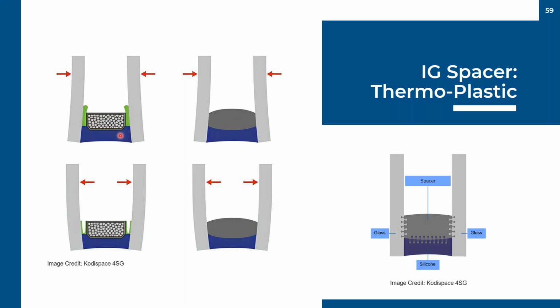Now, many times the problem with windows that we see all over the place, insulated glass windows, is they fog up, and that's an indication that the seals have gone past their useful life. And what happens with these spacer systems is that through the heat and cold fluctuations of the year, that sealed airspace can experience several different pressures. In the wintertime, these seals, that primary seal, can experience a pinching effect. And then during the summertime, you can see a pulling effect at those seals. Over 20 or 30 years, you'll see that eventually release that seal, and that's when we see the fogging. And it's at that time that owners will start to consider maybe we need new windows because the seals have gone, and they start thinking about replacing the windows. So what if we had a longer lasting seal?